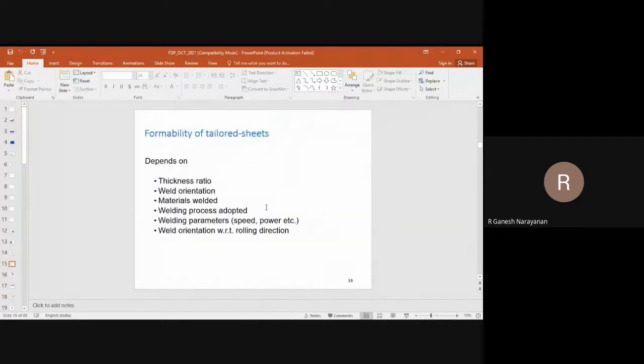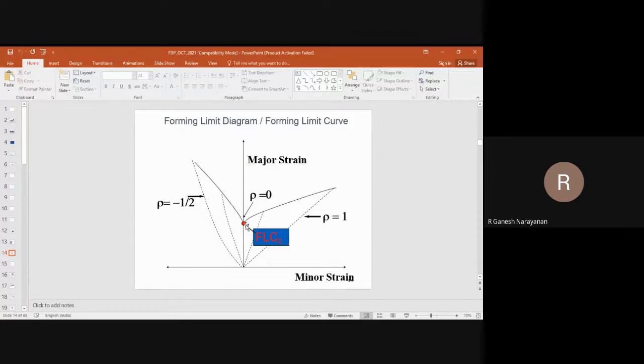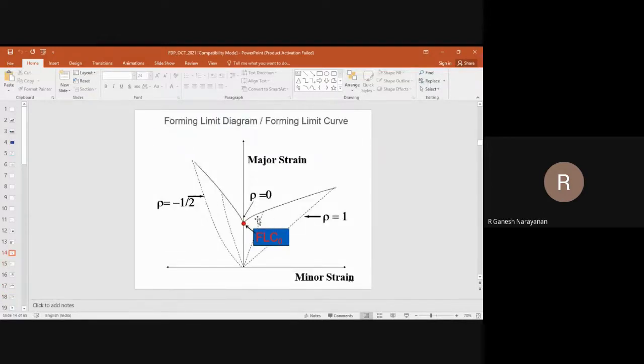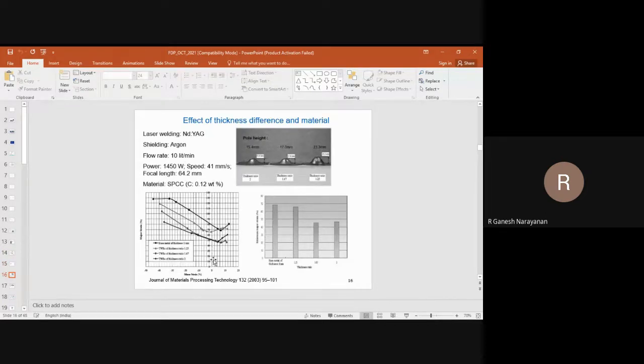Similarly, several combinations are possible, and they made welded blanks from this, and they have quoted FLC 0. FLC 0 means again this particular parameter, not the entire FLC, only this. And you will see that for the laser welded blank, it is given as 41, 38. This is in percentage. See, these are all strain values. I will give you an example here. You can see this: on the Y-axis you can see 0, 10, 20, 30, 40. On the X-axis you can see 10, 20 on the left hand side, on the right hand side. On the left hand side it is minus, because this is going to the tensile side. These are all values in percentage. Tensile percentage, you can say 10%, 20% strain, 30% strain, like that. Sometimes in decimals also you can write 0.1, 0.2, 0.3. Does not matter.